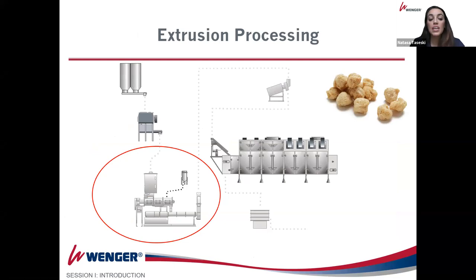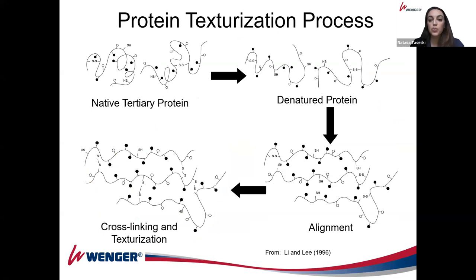So when it comes to extrusion processing, the extruder is really the center of our process. And what happens inside of the extruder when it comes to textured proteins? This is best described by this image, where it shows the native tertiary protein of your raw materials, which is really the configuration that the proteins within your raw materials would typically be found in. And then with the cooking inside of the extruder, you get a denatured protein. And then once you've denatured the protein and you've unraveled and broken some of those secondary bonds, you essentially go into realignment and cross-linking and texturization. So the alignment and the cross-linking typically takes place in the die. And this is really dependent on the type of die configuration and die design, what kind of alignment you will achieve.